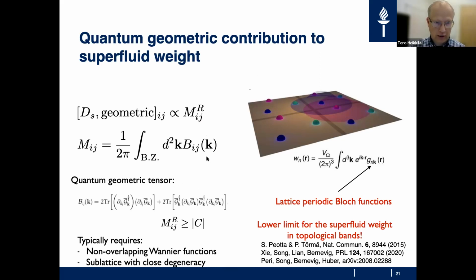I will not go into the details of this too much, but basically the point is that from this quantum geometric tensor you can calculate, for example, Chern numbers. And if you have a finite Chern number for your system, then there is actually a lower limit for the superfluid weight, so that you can have a completely flat band and still have a finite superfluid weight.